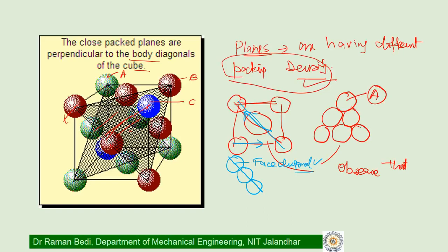What will be the effect of this, we will see in our discussions later, that is, the effect of this on the properties of the materials. We have already seen that this may influence the stiffness, because you have different directions, and the interatomic spacing along different directions happens to be different. So the interatomic spacing along this direction is different from what is here along this direction, which means they may have different properties in these two directions, or anisotropy may be available to us at the unit cell level, or I will say at a micro level.